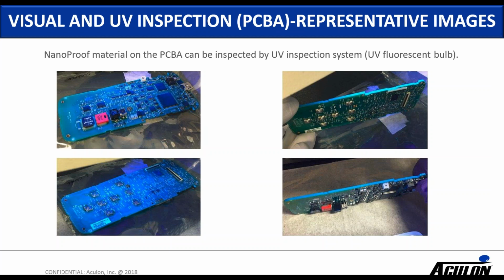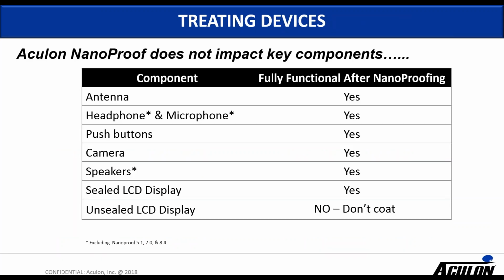All of the NanoProof coatings come standard with a UV dye. They can also be supplied without a UV dye if that's desired. We do get that request occasionally for some applications. Another nice feature is some of the NanoProof line, not the thicker variants, but some of the thinner variants, can essentially coat the entire device. And there's no negative impacts on coating the antenna, headphones, push buttons, camera, speakers. They're essentially so thin that there's no impact there. But again, that applies to our thinner coatings, not necessarily the 5, 7, or 8.4, which are all thicker than 10 microns.